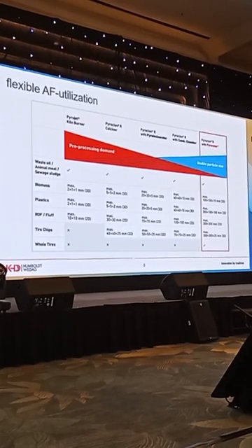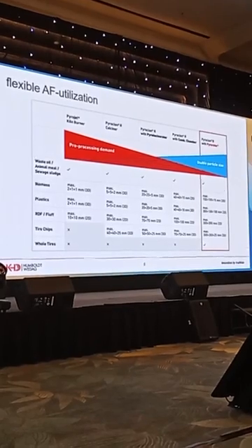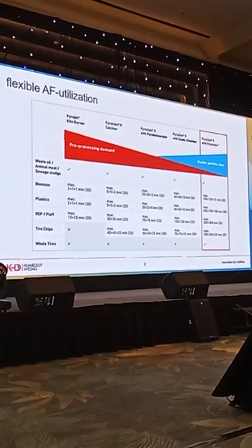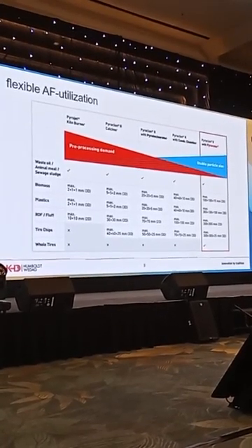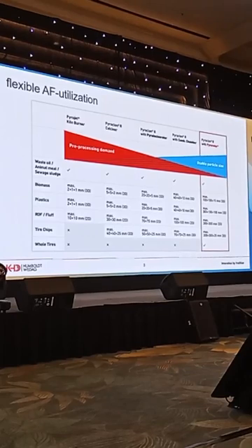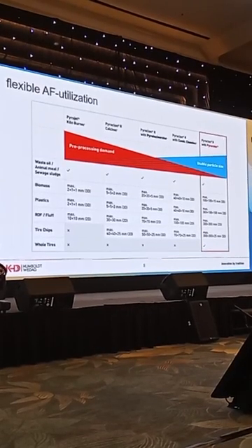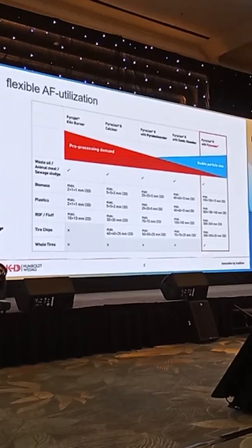So now you see there's a rough overview of this usage, and at the end it's just a question of the pre-processing demand and the usable particle size, which equipment should be used. So this means if you're getting already highly pre-processed material from your suppliers, you can use a more simple system, an easier handling system. But you have to spend a lot of money on the pre-preparation process to get it into the right size and the right amount, because the amount is also a very critical point when using alternative fuels. And there's also the possibility to have it in a low pre-processed size, and then use, for example, the pyro-rotor.